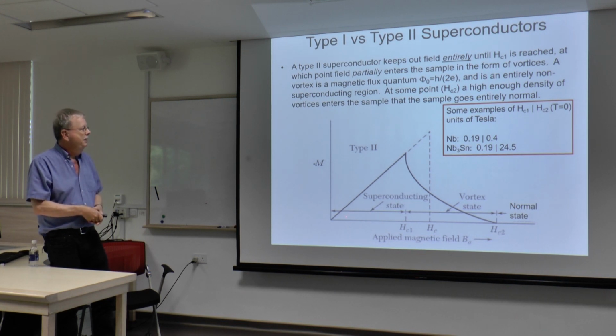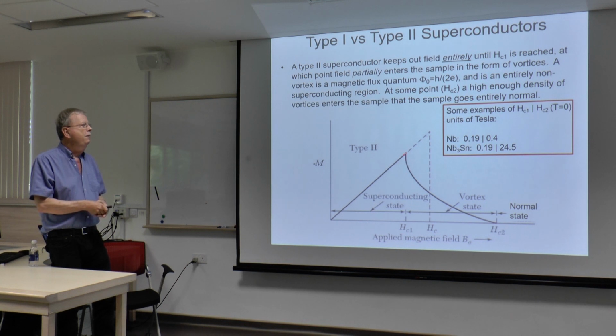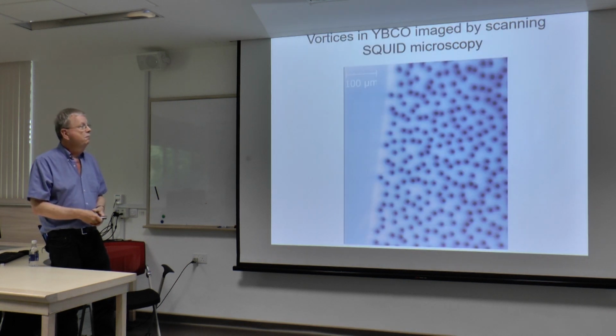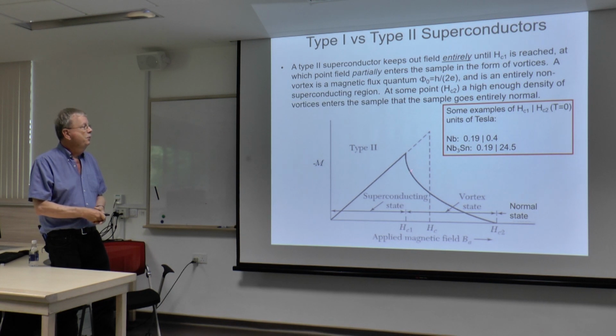A type 2 superconductor is perfectly diamagnetic up to some lower critical field, known as HC1, which can be quite small. And then flux lines start to penetrate in. Here are some flux lines in the yttrium barium copper oxide high TC cuprates, which we'll talk about later. Please notice that this is in no sense an ordered lattice of flux lines. The black spots are flux lines. This is fairly random. We'll come back to that. So from HC1 up to an upper critical field, where the entire sample is threaded by flux lines and it's entirely normal, that's what happens to the superconductivity.